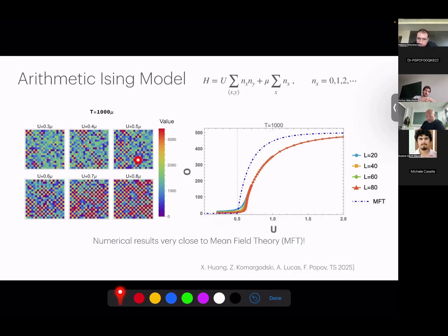On the left, you can see some typical configurations of this model at this temperature. You see here you have a gas, and if you increase u, around u of 1/2, you start seeing this checkerboard pattern, which indicates a solid. But an interesting thing is that if you do this in mean field theory, which is not supposed to be reliable, you get results which are very, very close to the actual results. So that's a little bit of a puzzle, and it's not clear why they're even close. And the question now is, can we understand why this is close?